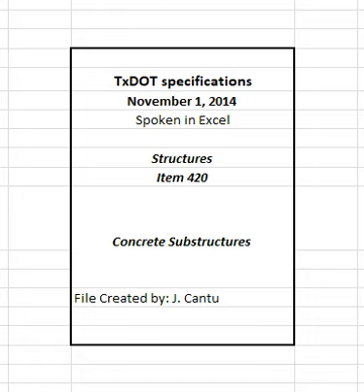Chip away all loose or broken material to sound concrete where porous, spalled, or honeycombed areas are visible after form removal. Repair spalls in accordance with the procedures outlined in the concrete repair manual available on the department's website. Clean and fill holes or spalls caused by the removal of form ties, etc., with latex grout, cement grout, or epoxy grout as approved. Fill only the holes. Do not blend the patch with the surrounding concrete.